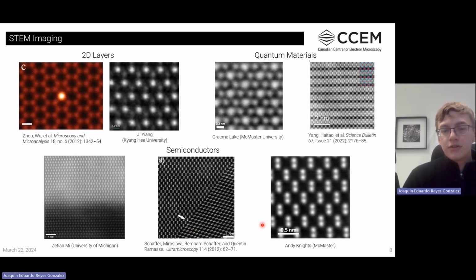And you can even do just your standard silicon sample, which we also acquired here at CCEM from Andy Knight's group. This is 100 kV. You can see those silicon dumbbells very, very clearly defined. It's a very nice image given.